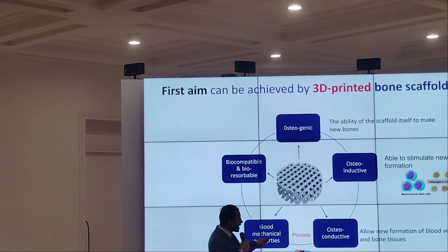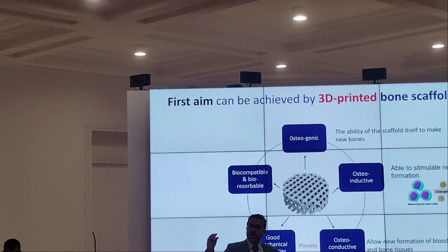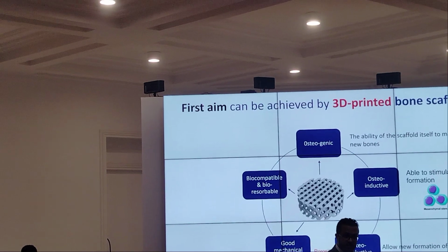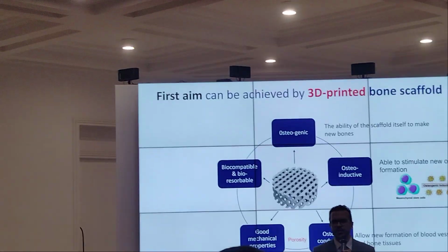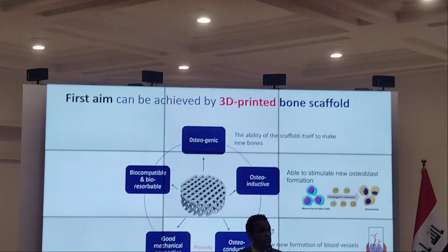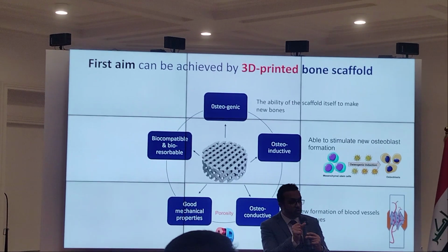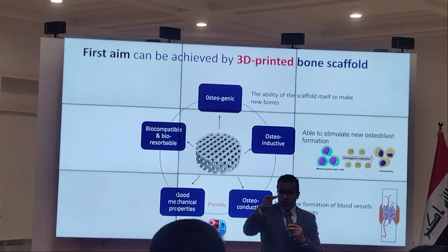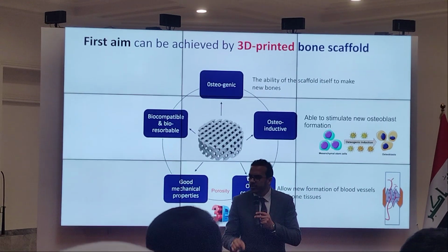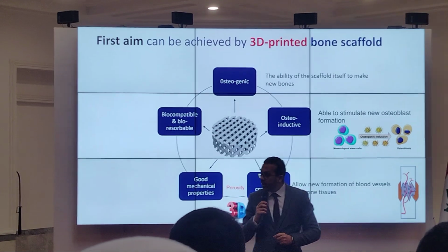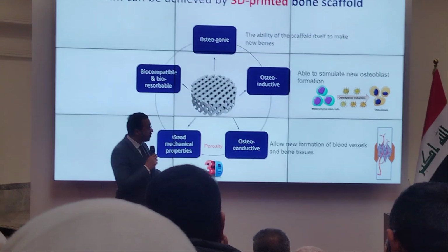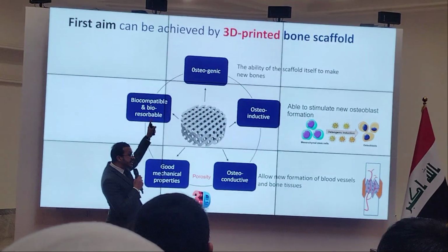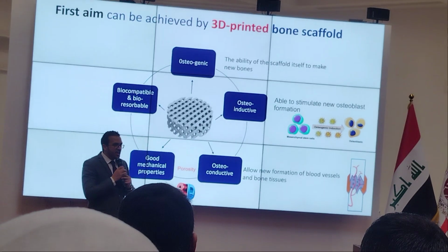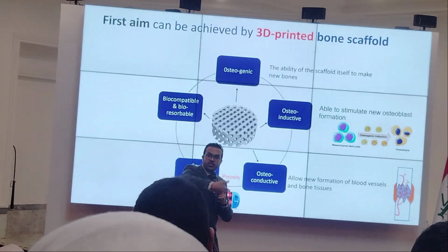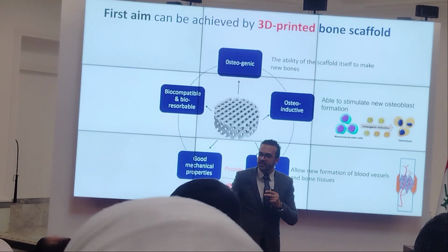And also we can control the mechanical properties of the scaffold itself. We need this scaffold to be impact resistant. So we can control the mechanical strength of this scaffold by controlling the porosity and the infill density of this scaffold. Moreover, this scaffold is biodegradable and resorbable. So after the growth of new bone, this material will disappear.